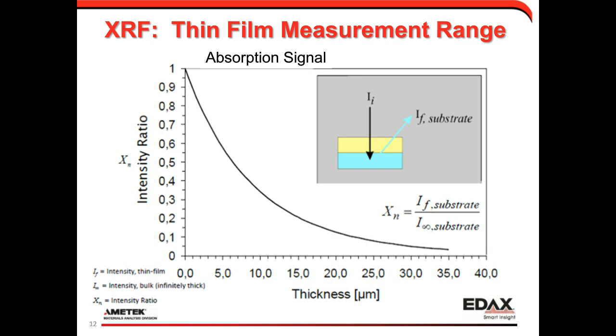But when you have a very thin layer, then our intensity ratio is going to be near a value of 1 because we're measuring the substrate signal now. And as we get a thicker and thicker layer, our intensity ratio drops down to 0 because the top layer absorbs most or all of the substrate signal at that particular point. So you have sort of the inverse plot for this.